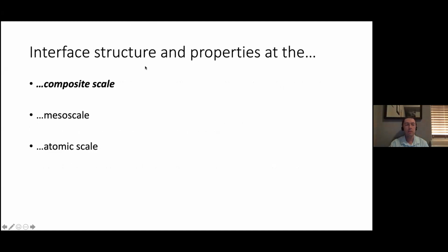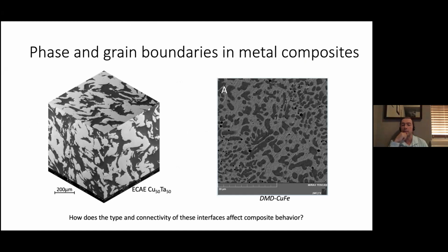So let's move on to the first one, interface structure at the composite scale. Let me just make clear what I mean by that. At the composite scale, here are examples of 2 composites. The one on the left is a composite of copper and tantalum in 50-50 proportions. This one is made by equal channel angular extrusion. It's a kind of processing method that you can use for changing the internal structure of composites. The one on the right is a copper iron composite made by direct metal deposition, which is a kind of additive manufacturing of metals. And in both cases, you can fairly easily see that there are phase boundaries, right?